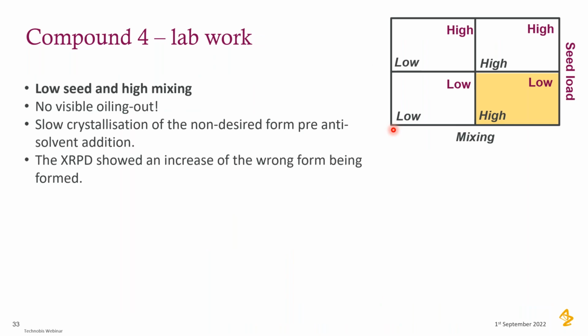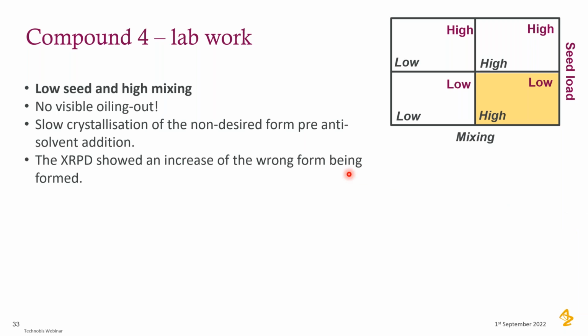So when we went this time to low seed but high mixing, in this part of the design of experiments, we observed no oiling out, so one gain. Yes, no oiling out, that's great. The crystallization was slow, but it ended up being slow with a non-desired form. So actually we ended up at the end with a mixture form. So with low seed and high mixing, we avoid the oiling, but we're not avoiding the fact that we're not controlling the form.